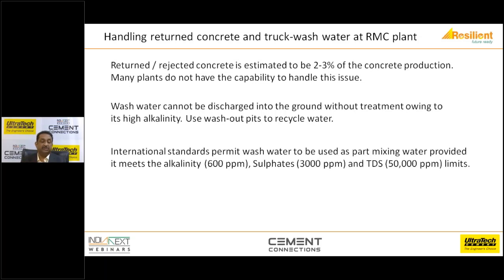You can have different methods to do this, but if you recycle this water, the international standards, whether it is the ASTM or the European or the British standards, permit the recycled water to be used back in concrete, provided you can establish that the concrete made with the recycled water is at least 90% of the concrete you normally batch. Then there are limits to alkalinity, sulfates, and TDS, which make sure that you can use this as part of 30%, 40%, or 50% of the mixing water, and you're recirculating the water back. So you are avoiding wastage, and second, you are conserving water, which is a very precious resource.